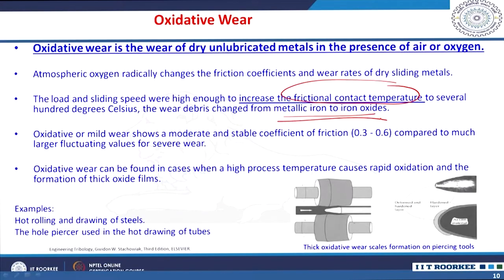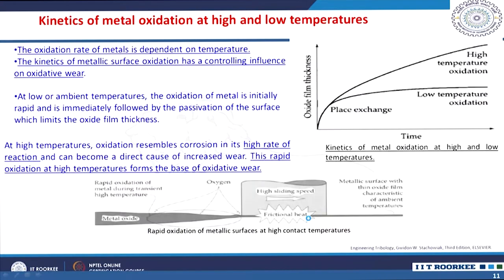Oxidative wear or mild wear shows a moderate and stable coefficient of friction compared to much larger fluctuating values for severe wear. Oxidative wear can be found in cases when high process temperatures cause rapid oxidation and the formation of thick oxide films, so you will have more material removal by this oxidative layer removal. Examples you can see are hot rolling and drawing of steels, and the hole piercers used in hot drawing of tubes. You can see thick oxidative wear scales forming on the piercing tools.